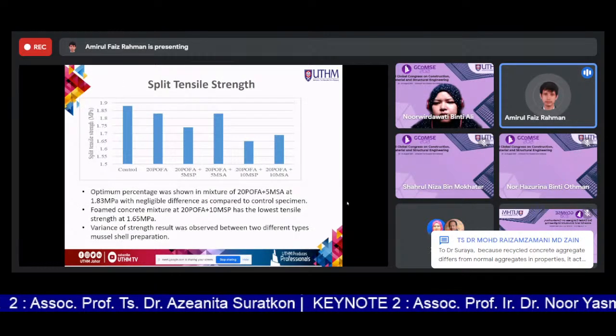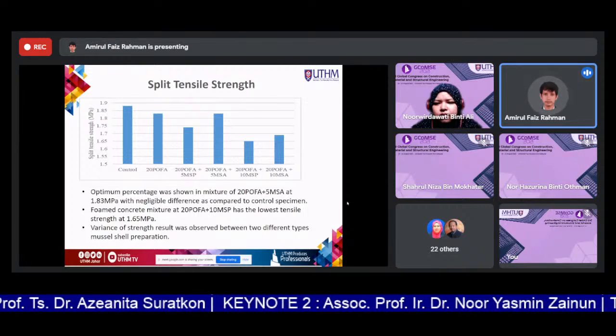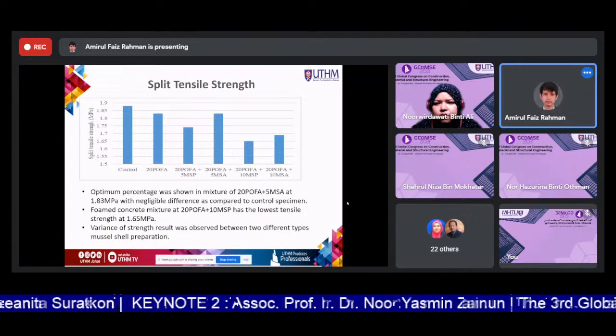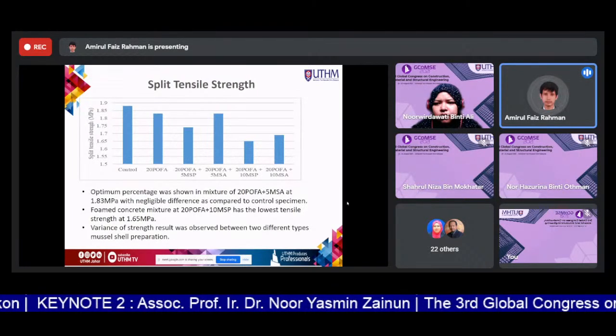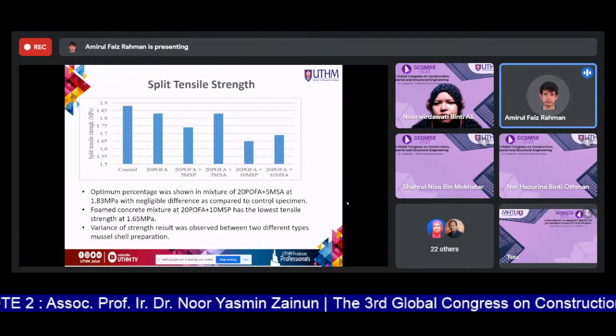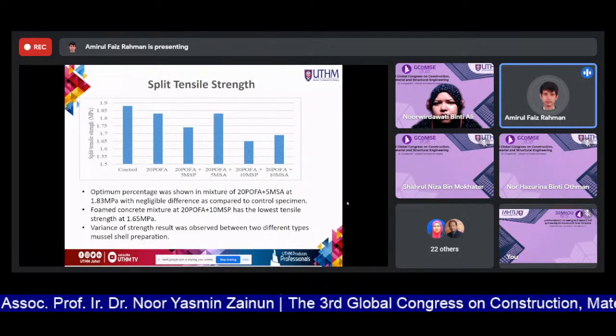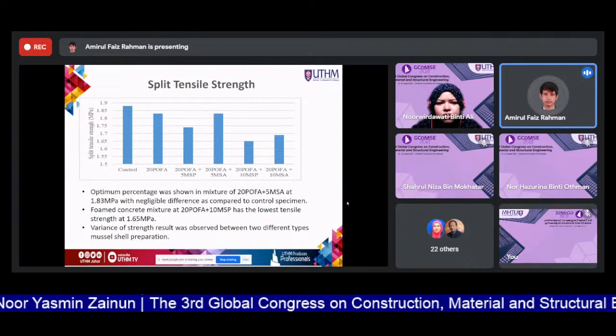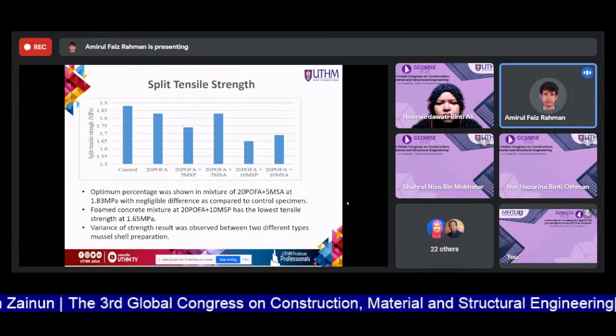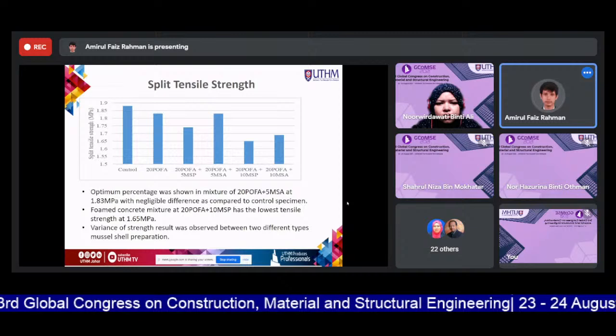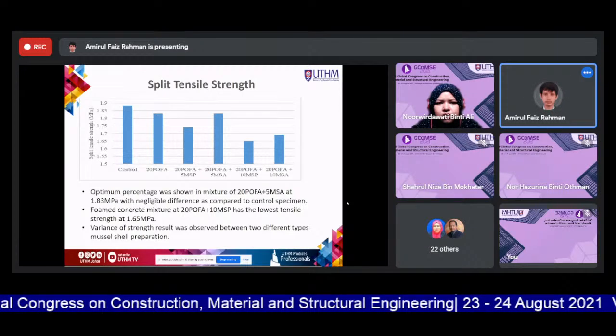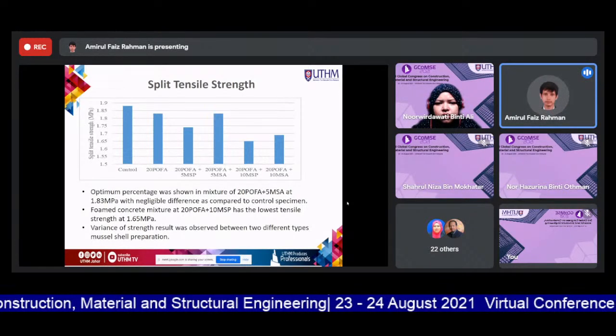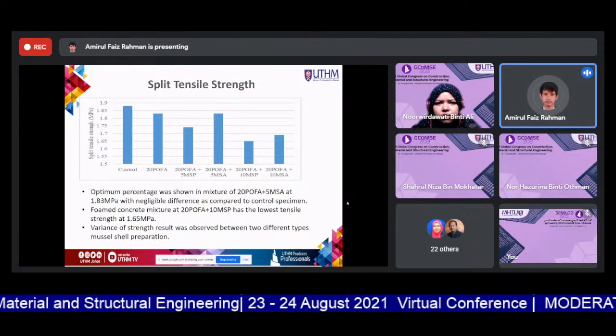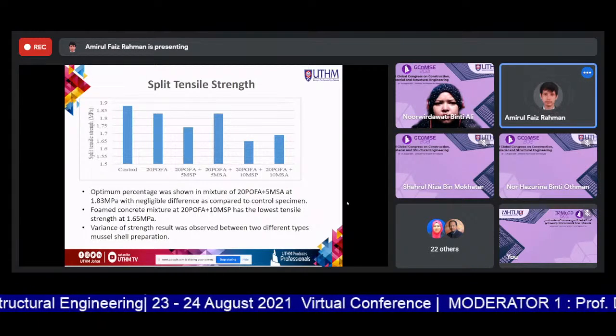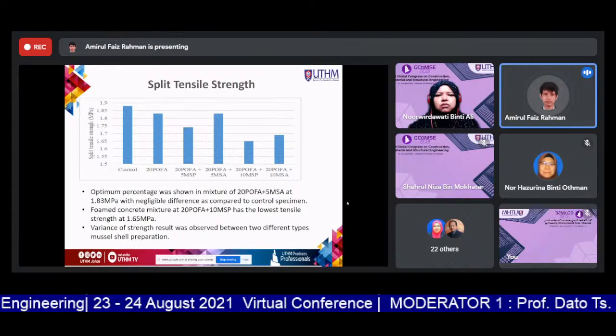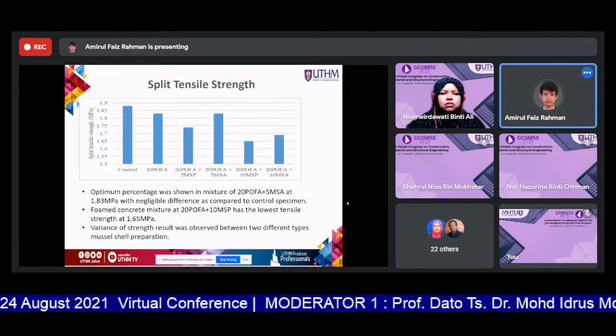Next, for the split tensile, based on the result, it shows that the mixture 20% POFA and 5% MSA shows the closest value with respect to the control specimens. And then the variance of the strength result was observed between two different types of mussel shell preparation, similar to the compressive strength result.